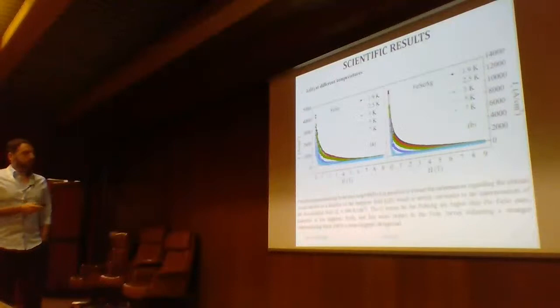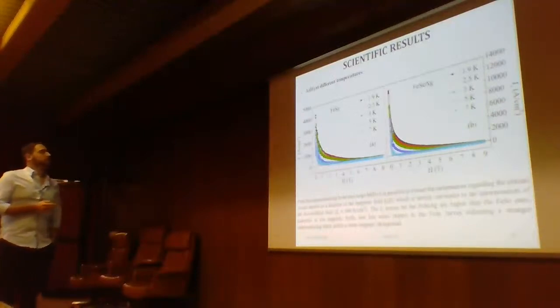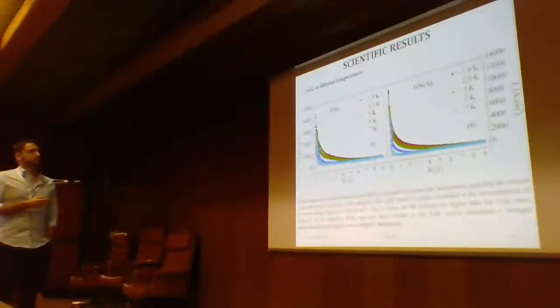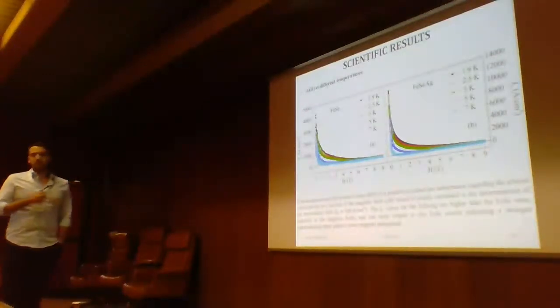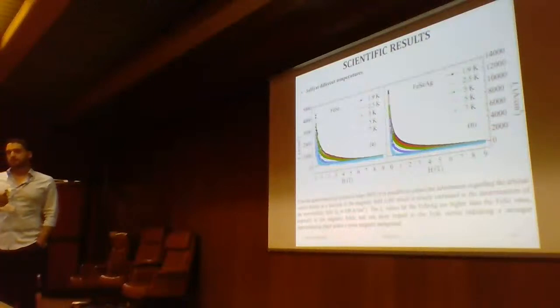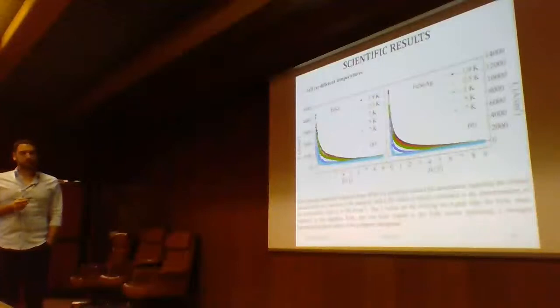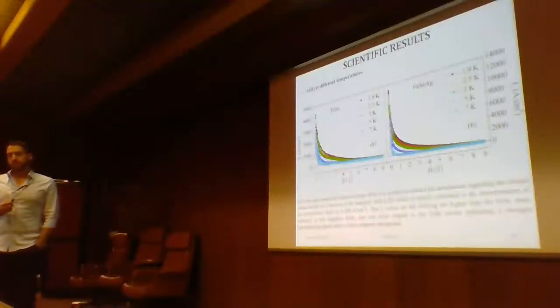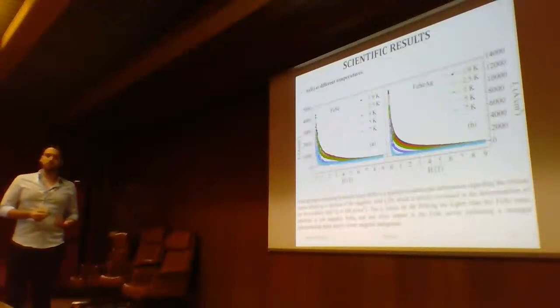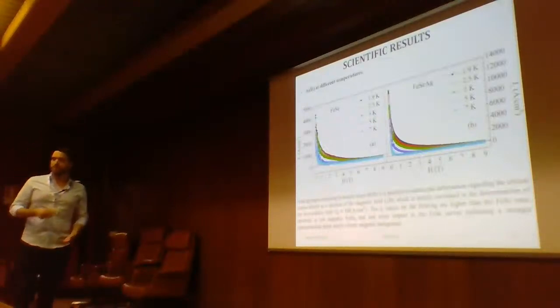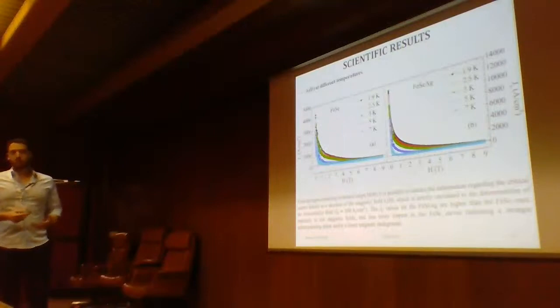The second type of characteristic that we have observed is the critical current density as a function of magnetic field at different temperatures. Now, what is the critical current density? The critical current density is a very important property and characteristic of superconductors because it is the maximum current density that you can put in your sample without having dissipation. So also for the application of superconducting magnets and superconducting wires, this is very important because you want to avoid dissipation